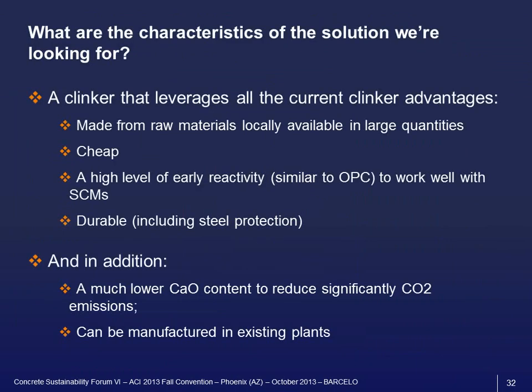So instead, we are proposing an out-of-the-box solution. So what are the characteristics of the solution we are looking for? We are looking for a clinker that leverages all the current clinker advantages, so something that is available largely locally, which is cheap, so nothing fancy, with a high level of early reactivity, at least the one of OPC, to work well with SCM, and that would be durable, including steel protection, which discards all the solutions with CO2 curing and so on. And in addition, we would like a much lower CaO content in order to drive down the CO2 emission, and we would like this to be able to be manufactured in existing plants, because the plant is fairly expensive.